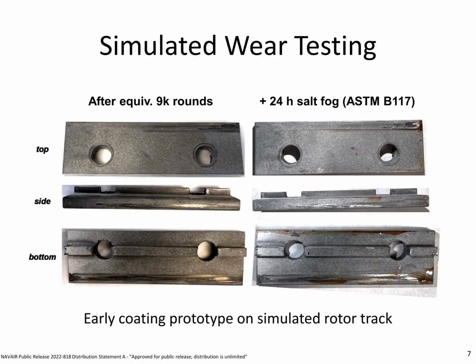This is one of the earlier tests that we ran with our coating system. It's actually changed quite a lot since these pictures were taken. So this is a picture of the rotor track after 9,000 rounds of wear, or basically 3,000 cycles on the wear tester, and then after 24 hours in the salt fog. So you can see where the wear shows kind of on the edges there and where you're getting down to bare metal. So now with a slightly changed coating, we can get to 15,000 rounds. You really don't see that much wear, and we can pass 7 days in the salt fog chamber, which is the ASTM B117 method.